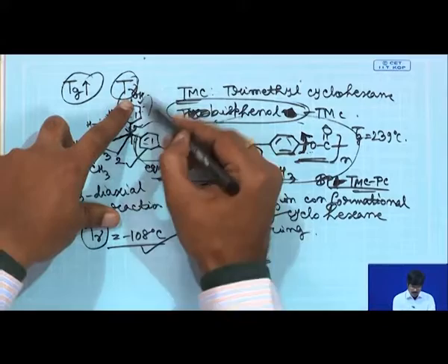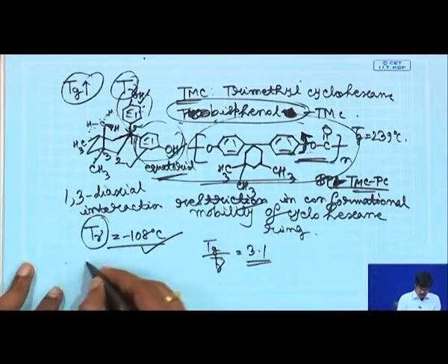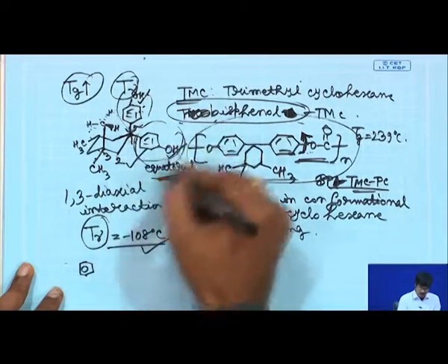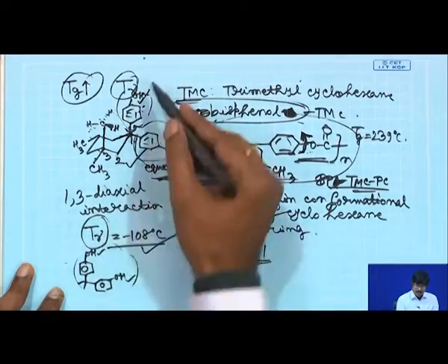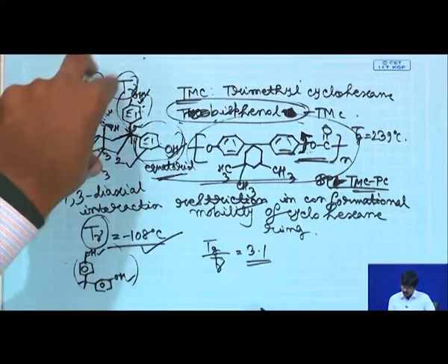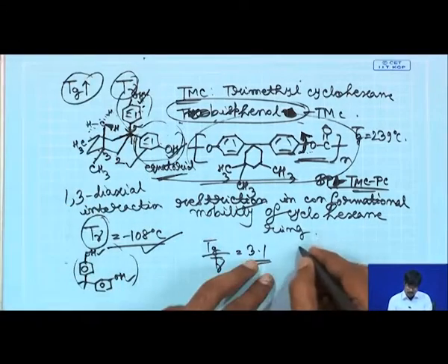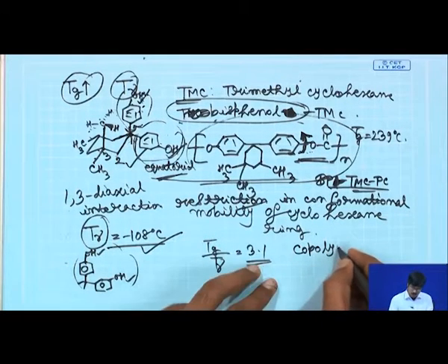Also, look at this phenolic OH group and the phenolic OH group of bisphenol A. If you look at this molecule and at this molecule where you have 2 methyl groups, the phenolic groups in bisphenol A and the phenolic groups in this bisphenol trimethyl cyclohexane have similar reactivity. So, since they have comparable reactivity, you can actually prepare copolycarbonates from them.